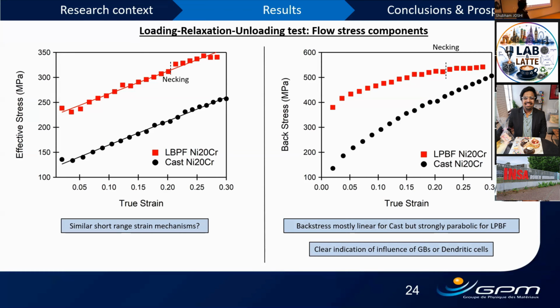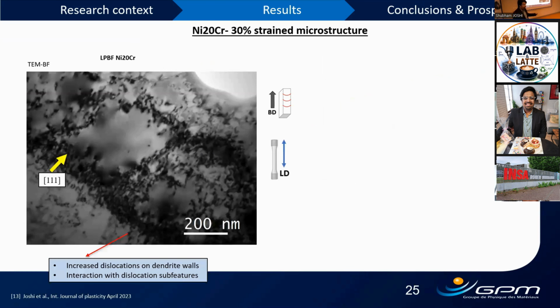And if we look at the strain hardening behavior, or at least the evolution of this back stress, it sort of replicates the parabolic hardening that we see in additive manufacturing samples. So as of now, we can understand that somehow back stress looks to be more important. And if you recall the definition, back stress means either grain boundaries or heterogeneous dislocations have to be involved. So now, coming back from our detour to the logical step that we decided to do first, TEM of the strained microstructure.